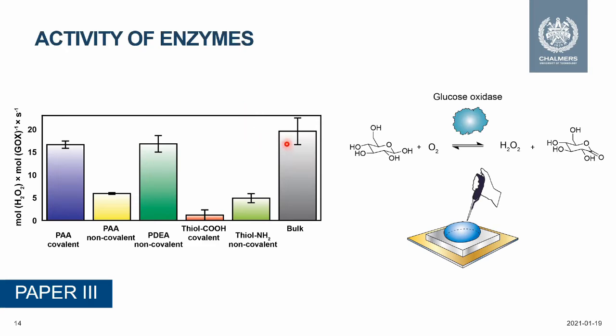The reason for the very high retention of activity in polyelectrolyte brushes is that they provide a soft, hydrated, three-dimensional support scaffold. This allows for high accessibility of the reactants and the products to diffuse to and from the active